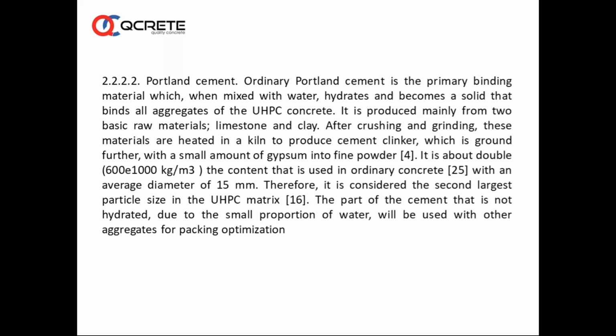Portland cement. Ordinary Portland cement is the primary binding material. When used with water, it hydrates and becomes solid and binds all aggregates of the UHPC concrete. It is produced mainly from two basic raw materials. We know all these things actually, which are basic, and the content that is used in ordinary concrete cannot be compared with this one. You have almost double the cement content in the UHPC. The part of the cement that is not hydrated due to the small proportion of water will be used with other aggregates for packing optimization.